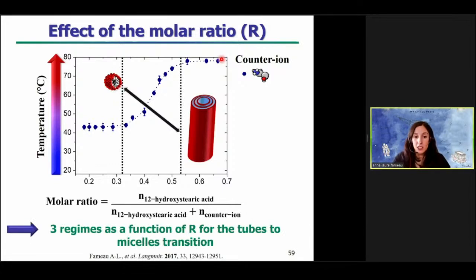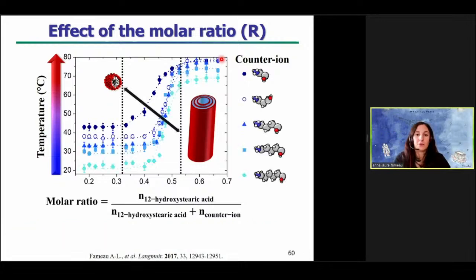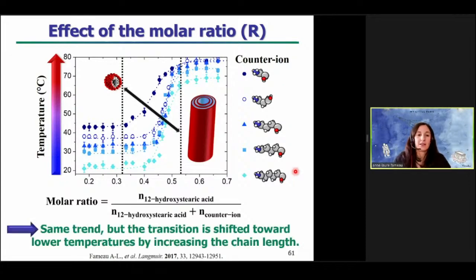So we observe 3 regimes as a function of the molar ratio for the tubes to micelles transition. And we can tune the temperature transition by tuning the molar ratio. Then we did exactly the same experiment for all the counterions from 2 to 6 carbons. And as you can see here, we observe again the same trend with the 3 regimes, but the transition is shifted to a lower temperature by increasing the chain length of the counterion. For example, for the counterion with 2 carbons, at low molar ratio, the temperature transition is around 42 degrees, and for the counterion with 6 carbons it is around 20 degrees.